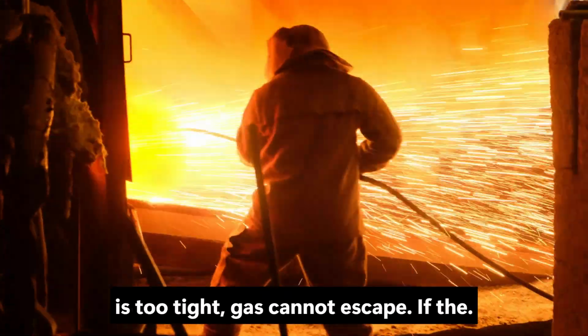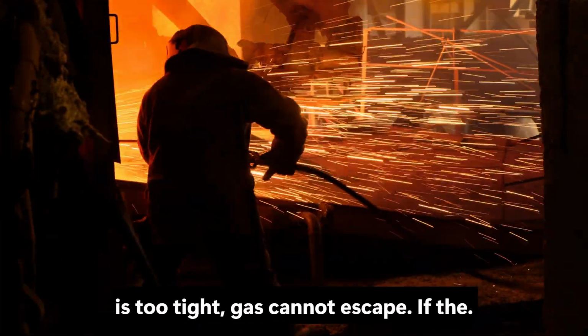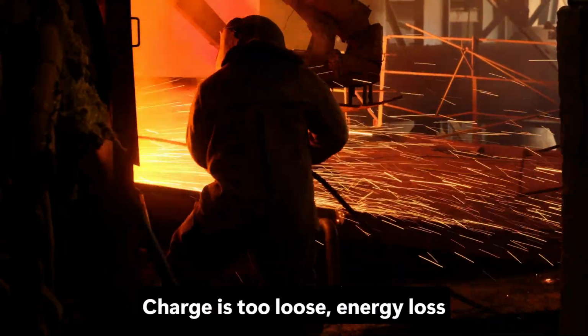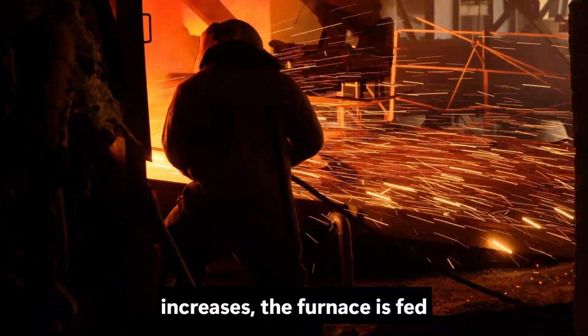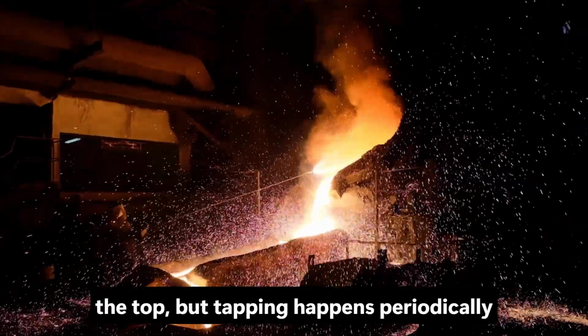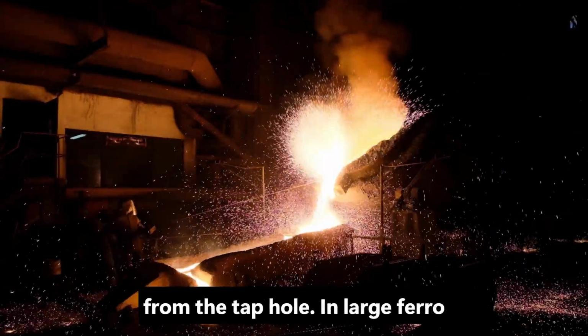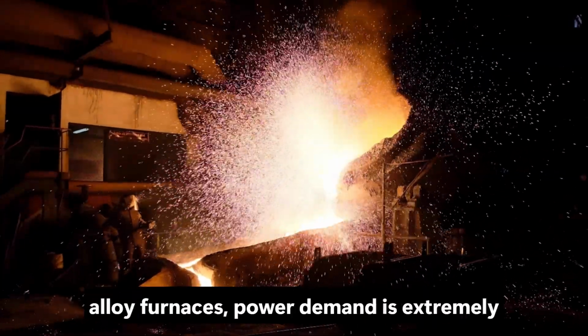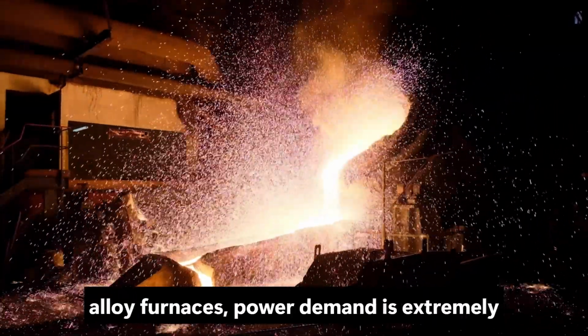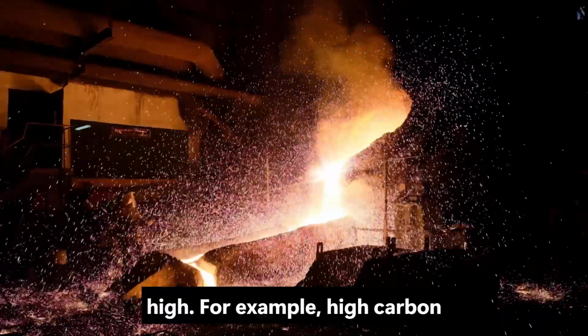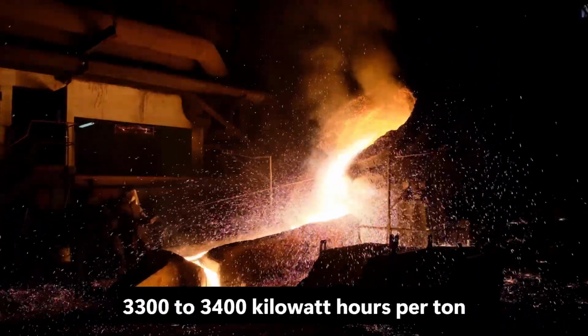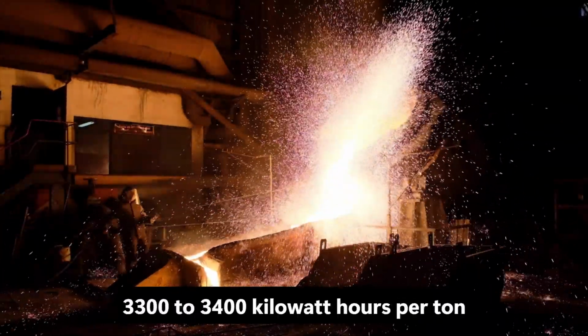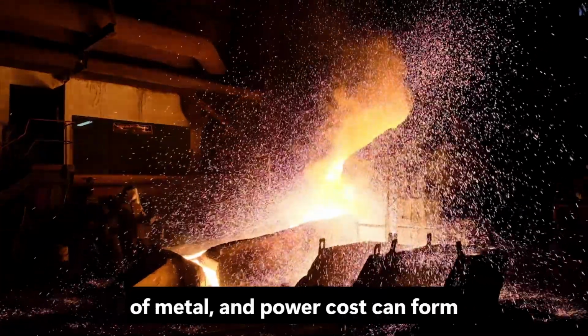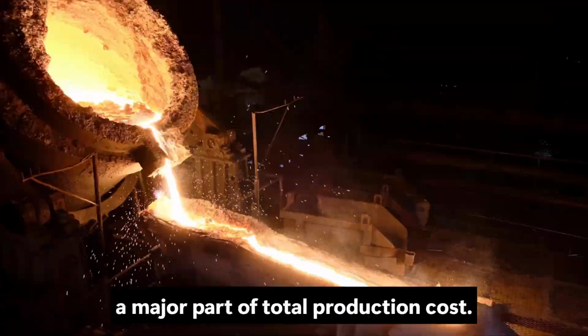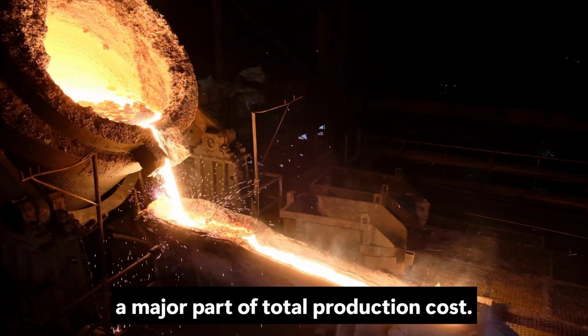If it is too deep, power distribution becomes poor. If the charge is too tight, gas cannot escape. If the charge is too loose, energy loss increases. The furnace is fed continuously or semi-continuously from the top, but tapping happens periodically from the tap hole. In large ferroalloy furnaces, power demand is extremely high. For example, high-carbon ferrochrome production may consume around 3,300 to 3,400 kilowatt-hours per ton of metal, and power cost can form a major part of total production cost.